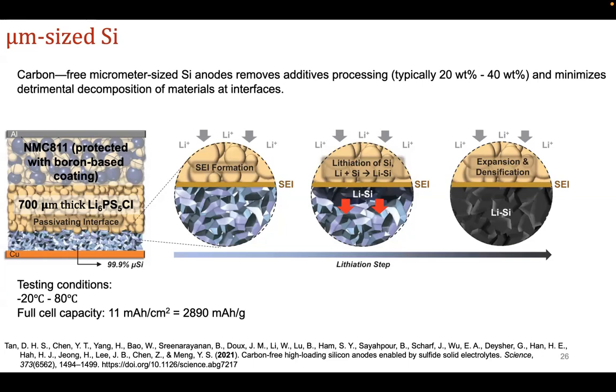You have delamination off of the current collector, so now you have less electronic conductivity. And on top of that, the SEI can also contribute to the isolation of the electrical conductivity of your entire composite. So not only is your electrode going through physical changes, being pulverized, but the SEI contributes to further isolation of your electrode material. Now, that's the case for liquid electrolyte. For solid electrolyte, you can now go back and you don't have the same challenges as you did with liquid electrolyte. So that's what they demonstrated here for this full cell, where you have